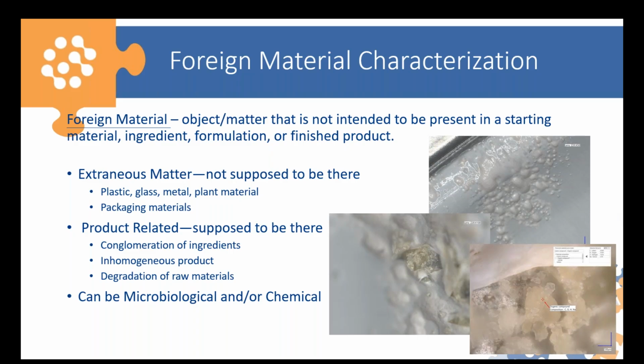You can see that's not really an appealing look. And so we worked to try and figure out, okay, what was causing this blistering? And so what we did is we took these high magnification images, we opened up the blisters, and what we found inside was this crystalline-like material. Then we took that material and analyzed it for its elemental composition using a laser-based elemental analyzer where we could target very specific locations. And we found that this material was primarily comprised of organic components, carbon, oxygen, hydrogen, but it also contained a significant amount of sodium. We were also able to isolate some of this material and analyze it by FTIR. And what we found was these crystals appeared to be the brine that had solidified.